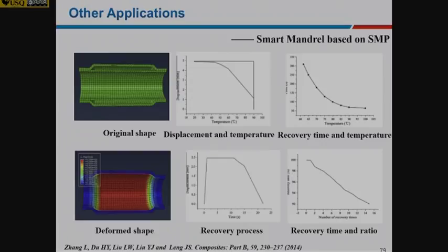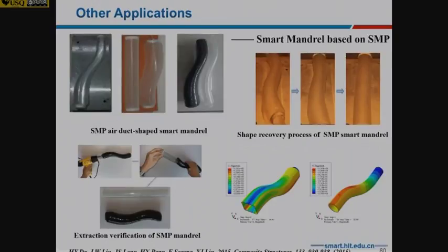And we also did some simulation work using FE modeling to see the deformation and the stress distributions. So this is another one for the air inlet. You see one side is a circle, another side is rectangular. So normally it's not easy to take off after filament winding. But with this one, SMP, you do filament winding. After that, the polymer becomes smaller and soft, then it is easy to take off from the composite tube inlet. So we also did some simulations.